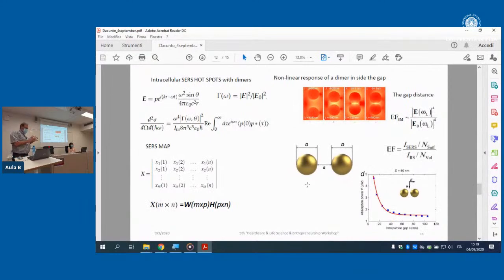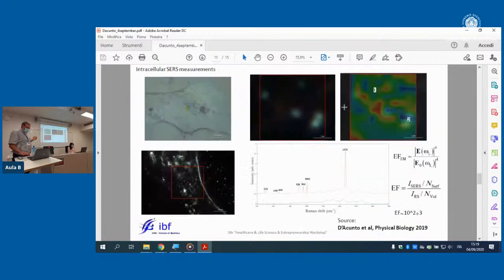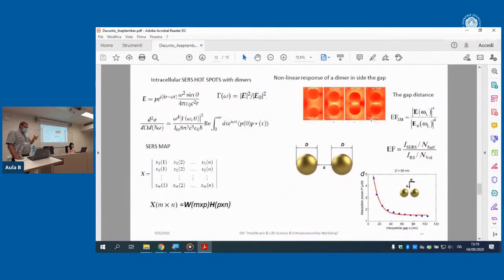And now we focus our attention on the possibility to solve the spectral mixture of what we are observing. What we are observing depends on the gap between the 2 nanoparticles, practically this region inside here. And this depends on the distance of the 2 nanoparticles, because the signal decreases exponentially with the increase of the gap between the 2 nanoparticles, depending on the polarization and the direction of the electromagnetic field. And also theory was improved to create a SERS map.